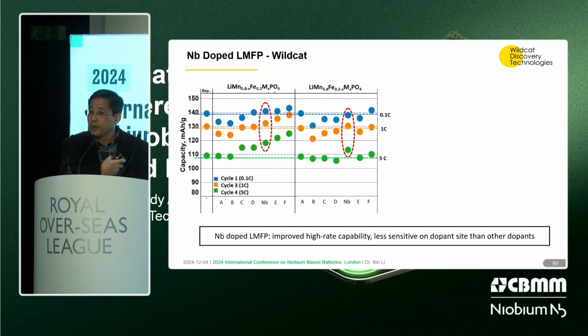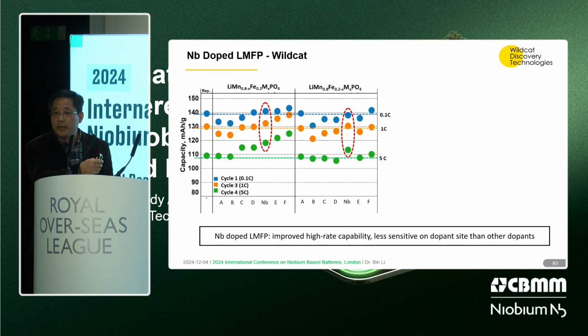Now, I want to demonstrate some of the niobium effect in the lithium manganese iron phosphate. Here we have different doping elements, but it depends on which side you dope. So here showing, this is the baseline. Here we're showing the doping on the manganese side, and there doping on the iron side. We show the different key metrics here: 0.1C discharge capacity, 1C discharge capacity, and 5C discharge capacity. The dashed line showing the baseline at each rate.